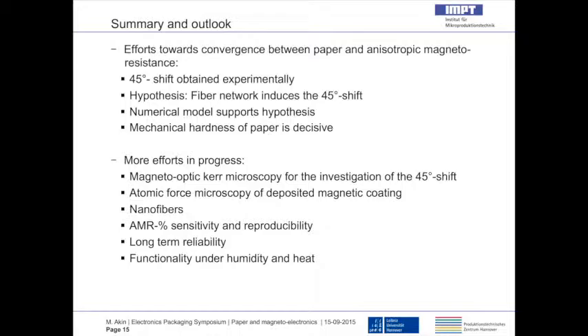What we are currently trying to do is look at that 45-degree shift in terms of how those domain walls form, and we want to do that with MOKE microscopy, which is actually made for highly smooth, polished surfaces. But we were already successful in seeing some information about the magnetization of the coatings on paper. We're also going to use atomic force microscopy to analyze the deposition and crystallization of those coatings, and we will assess the sensitivity, reproducibility, long-term reliability, and the functionality of these systems under environmental conditions like heat and humidity.